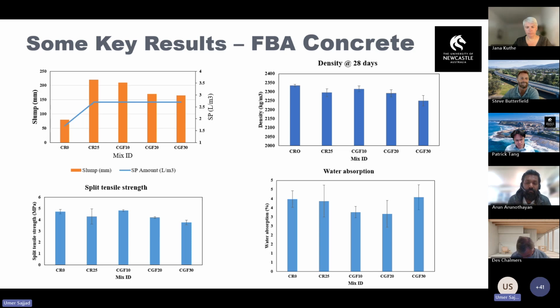And you can see the most preferable one is the CGF10, in which we have replaced 10% of cement with furnace bottom ash. Then we have the splitting tensile strength test, in which we have compared all of these 5 mixes, and we have performed the test at 28 days.